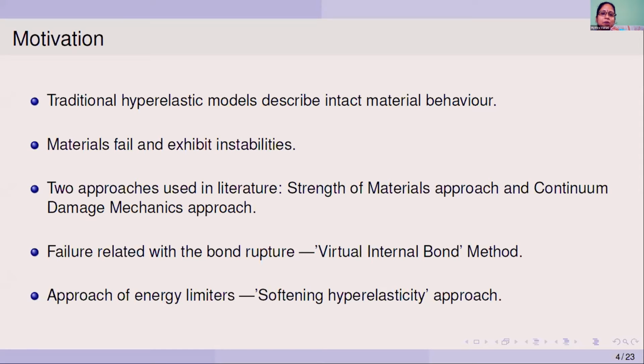However, its computer implementation in macroscopic failure problems is numerically involved, as it demands averaging of the interatomic potentials over a representative volume. So, in order to overcome the computational intensity of this method while preserving its sound physical basis, Volokh has proposed the softening hyperelasticity approach. This approach models failure by introducing energy limiters into the expression for the strain energy density function.